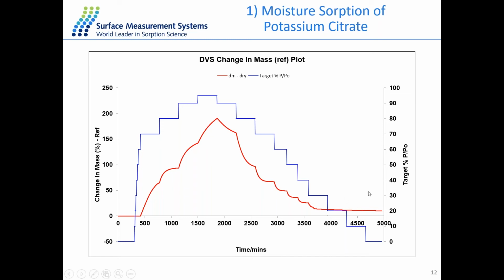And at the end of the desorption during the first cycle here, you can see it's not going back to 0. So that means this moisture sorption and desorption is an irreversible process. So the final sample is different from the original sample at the very beginning, with some water molecules still trapped inside of the material. And then we can plot the isotherm with the analysis software, basically just taking the equilibrium